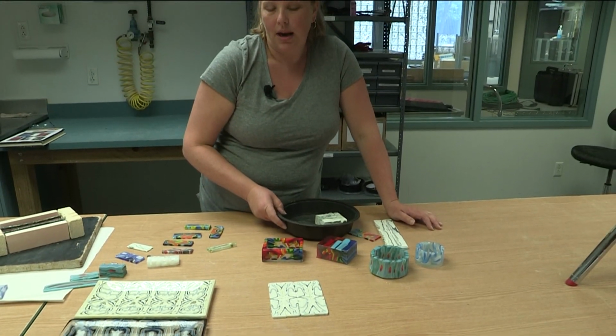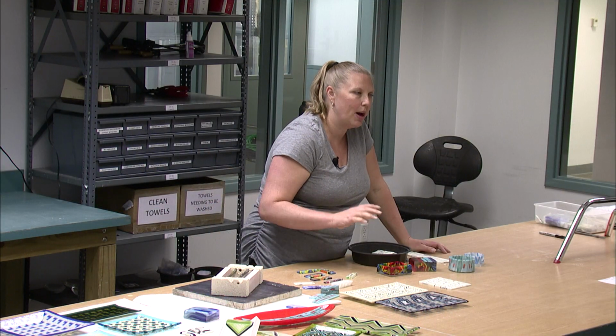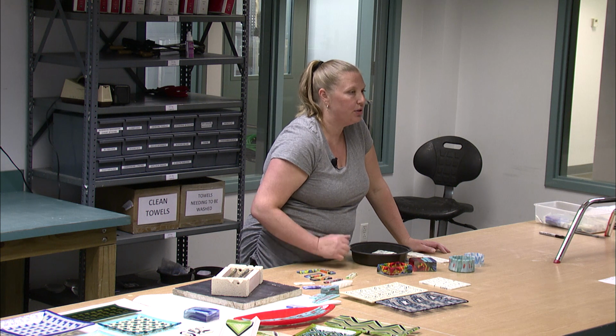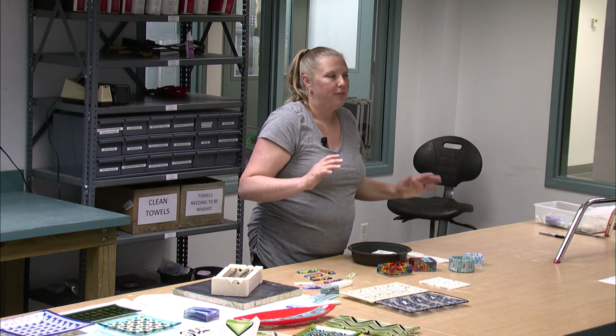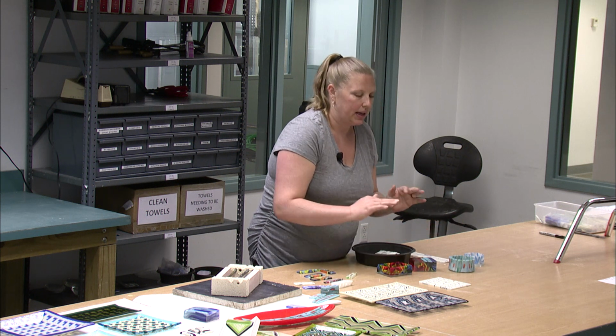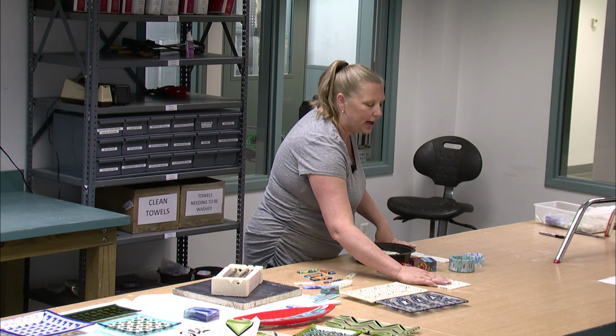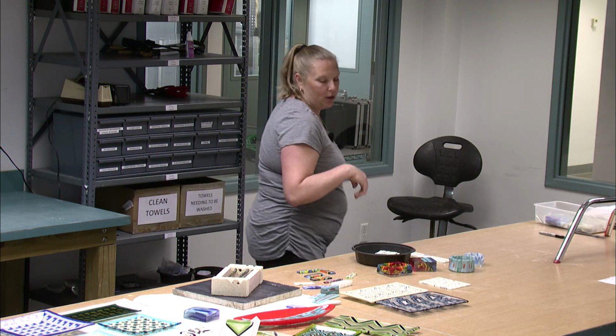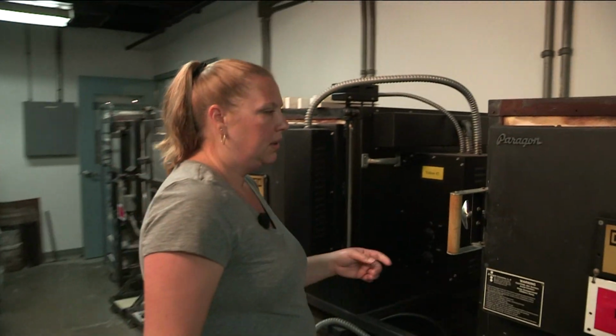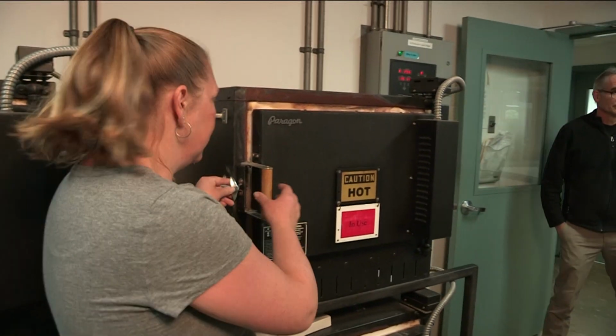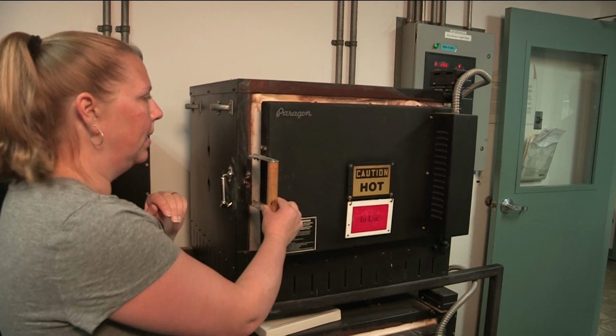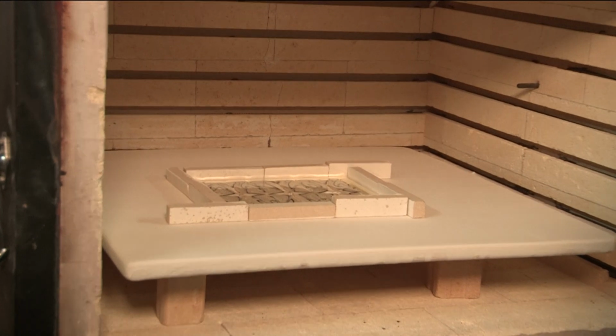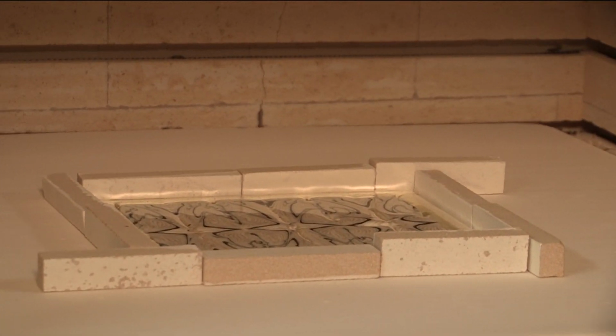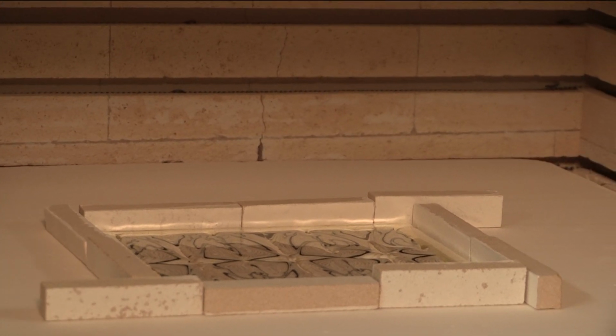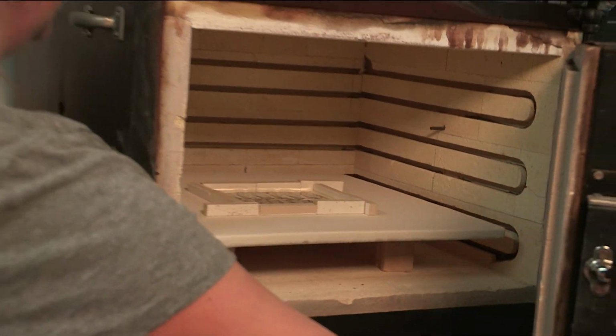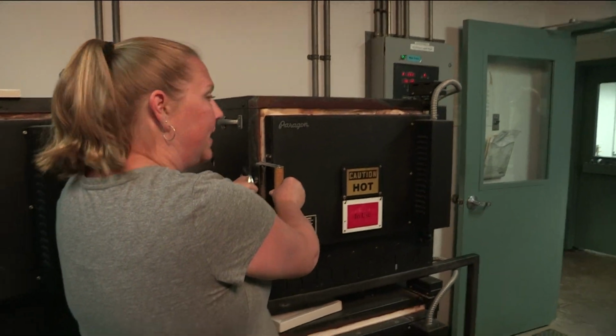So I turned on the kiln at approximately 9 o'clock, and I've programmed it to come up to 1490 degrees Fahrenheit. And it's going to hold there for about 15 minutes. And everything is going to just melt together and get nice and smooth. So let's go check out the kiln and see where it's at. Hopefully we can open the door and take a peek. Okay, so it looks like the kiln's at around 1100 degrees. We'll take a quick peek. It's pretty hot. And it's kind of already done a lot of melting. It's still forming together. But there you have that pattern I was talking about. And I'm going to close the kiln now just to make sure it retains its heat.